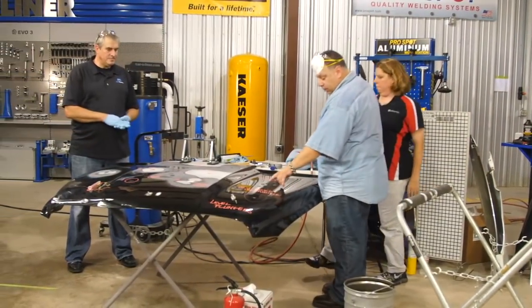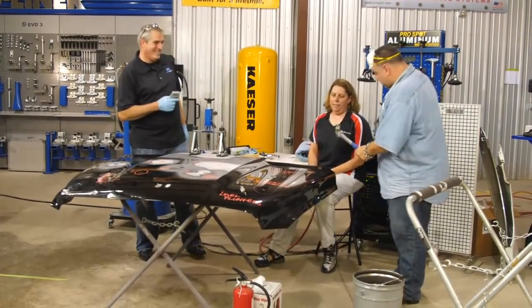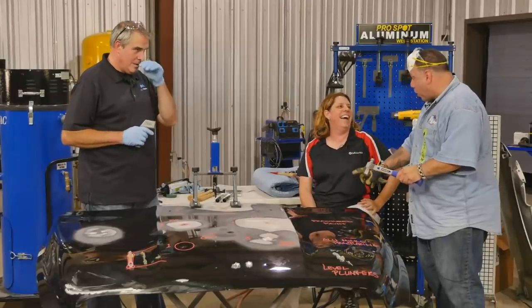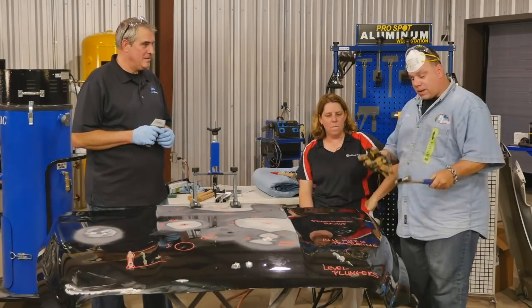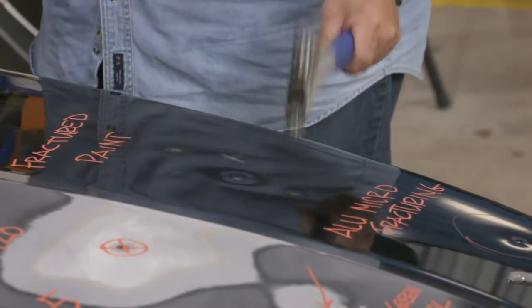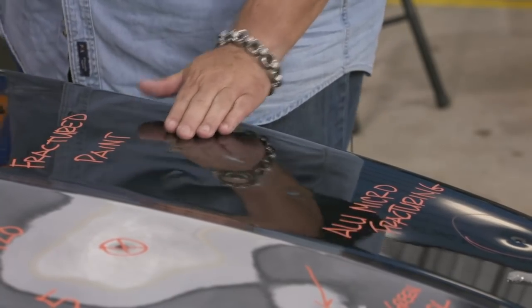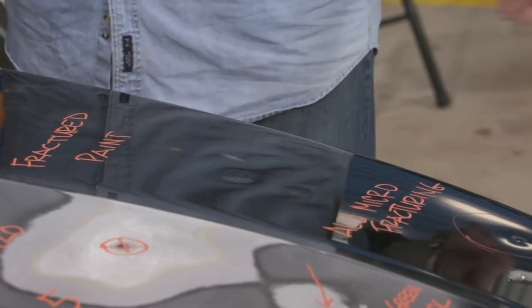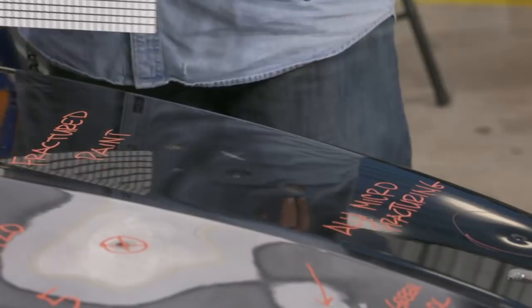Since we're going to talk about fractured areas first, we have a couple of spots here that we wound up heating up. I caused the same dent — basically I hit down on three spots, which aren't paintless repairs because we actually scratched it. I made similar ones on the opposite side, heated this up, and most of that dent actually came out. This is still a little bit there, and obviously I didn't touch that one. You can see the paint actually cracked, because I took room-temperature water and poured it on top — causing some micro cracking in the aluminum that we can't see but you can see in the paint. If the paint's cracked like that on a factory paint job, there's a major, major issue going on here.